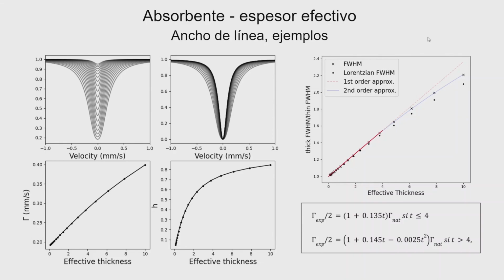So your line that should be Lorentzian, for an only absorption atom should be Lorentzian, starts to be no longer a Lorentzian line, because the height and the gamma don't increase in the same way. So you have an increase in the gamma, an increase in the height, that in fact starts to saturate. That is why they are also called saturation effects. It's quite obvious. If you increase too much your absorber, you can't absorb more than 100%. So you must have a saturation at some moment. You start to increase the absorption linearly, and you start to have a saturation.